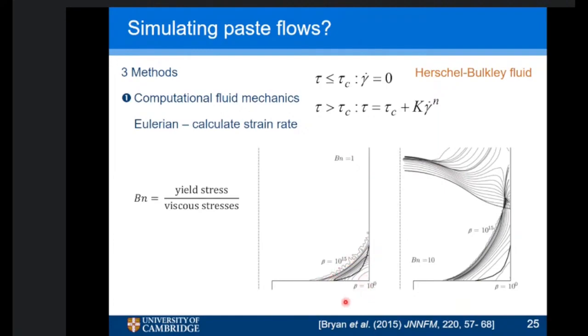Okay, for a slip coefficient of 10 to the 0. Okay, so this is a Navier slip coefficient. These things all change if you change the value of beta. And the solid line here is the shape that the material, in this case a microcrystalline cellulose material, took. It sort of basically hangs out in the corner. Everything else is sheared. It's all moving with max streamlines.